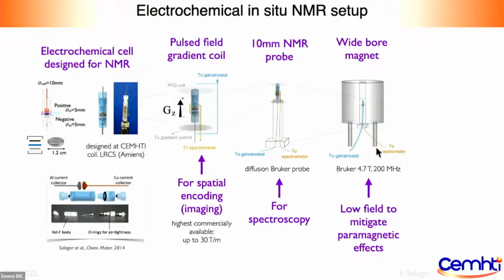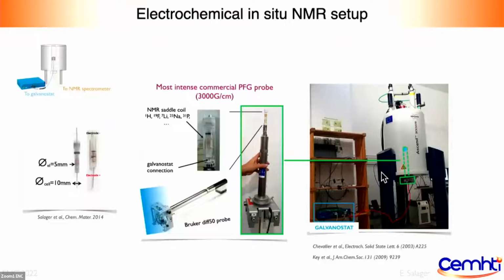Of course, we're not the first to do this. This has been developed by Le Tellier and expanded really by Clare Grey. And just to echo Joanna's initial presentation, this is what it really looks like inside the lab. This is the DIFF50 probe. We removed the gradient sheath so that you can see what is there. The electrochemical cell is in there, and we connect it here at the bottom for one electrode and at the top for the other electrode. Then we remove the dewar that is usually used to control temperature, and we replace it with the electrochemical cable so that it goes through the probe. It's actually very well shielded, and we don't get much problem with noise by doing so.